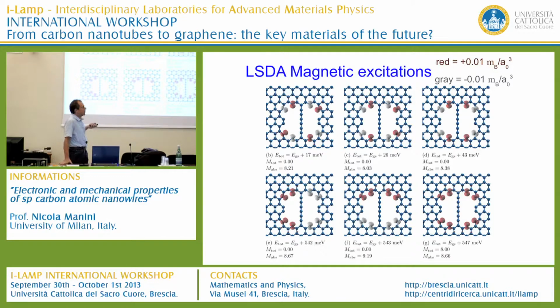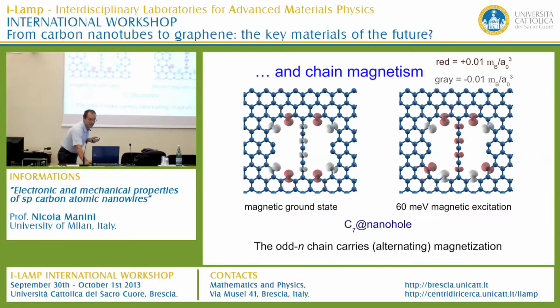But of course, it's not particularly important to see it in very much detail, because this specific hole is just one that we invented ourselves. There could be other holes with different magnetic structure, so it's not an especially important thing. The only thing worth remembering is that a graphene edge or a graphene hole is likely to have some kind of anti-ferromagnetic order of the dangling bonds inside. So indeed, there will be some magnetism there.